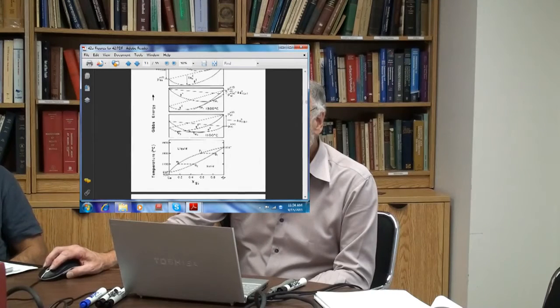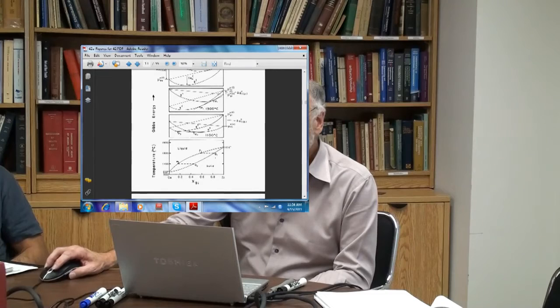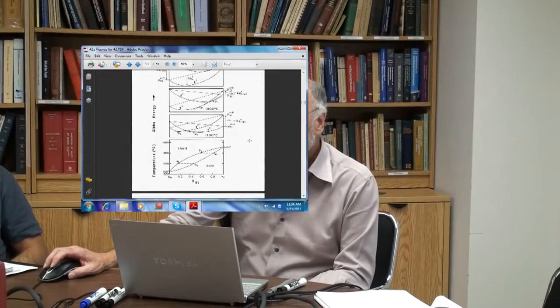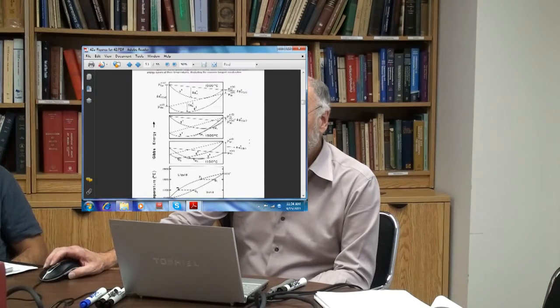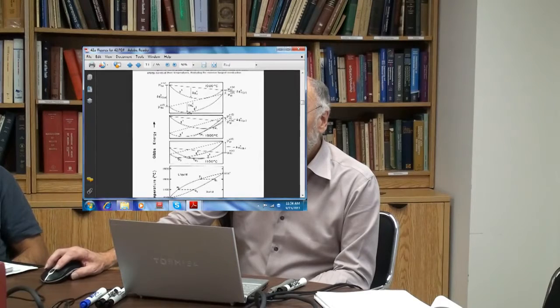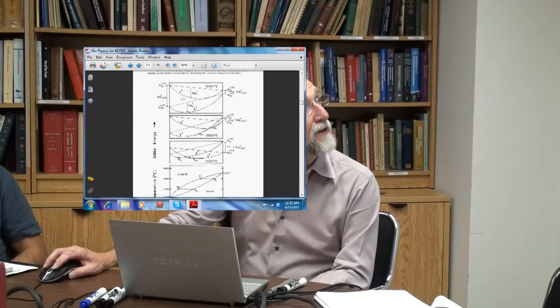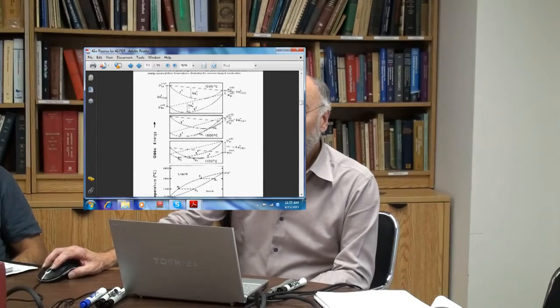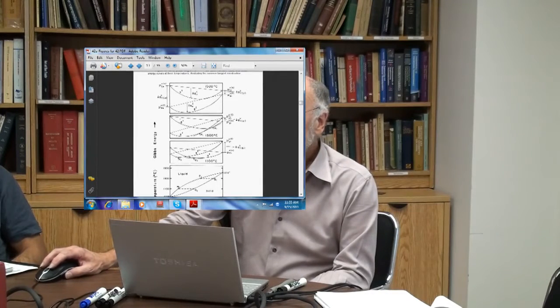Here's your germanium silicon phase diagram. You have the solid phase, you have the liquid phase, you have your two-phase region, melting points. If anybody wants me to go more slowly, let me know. Try to show how this is related to the Gibbs energy curves. So let's draw. Here we have the Gibbs energy curve for the solid phase, that's G of the solid phase. Here we have the Gibbs energy curve for the liquid phase, that's G of the liquid phase.